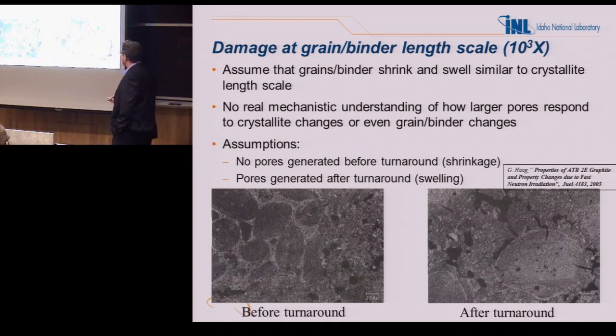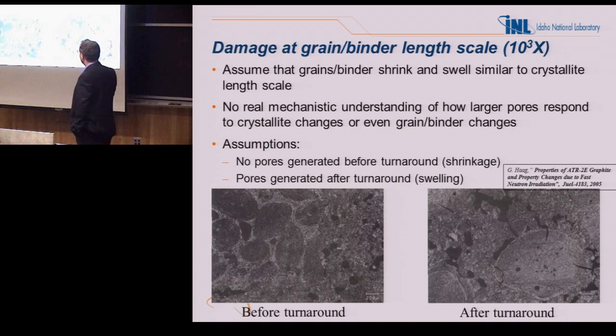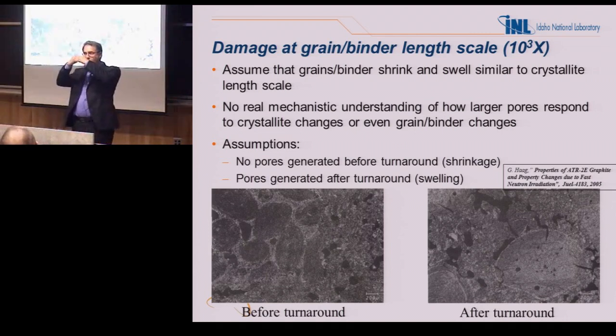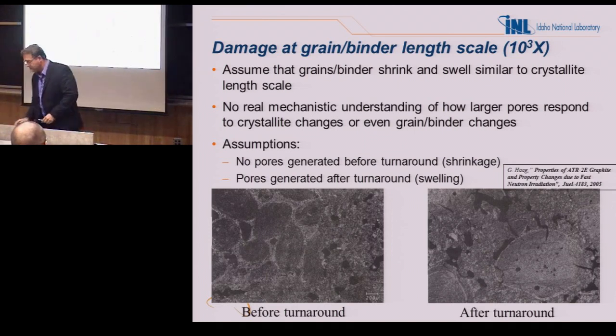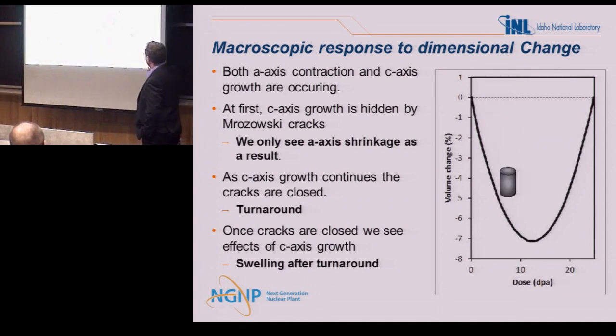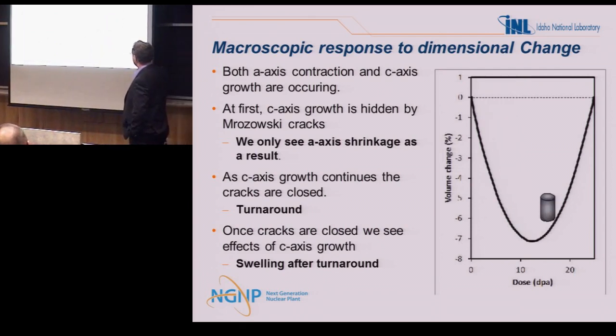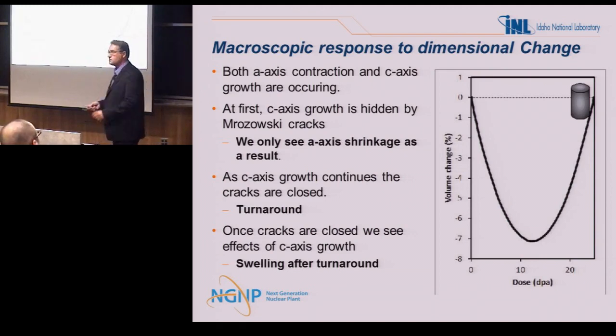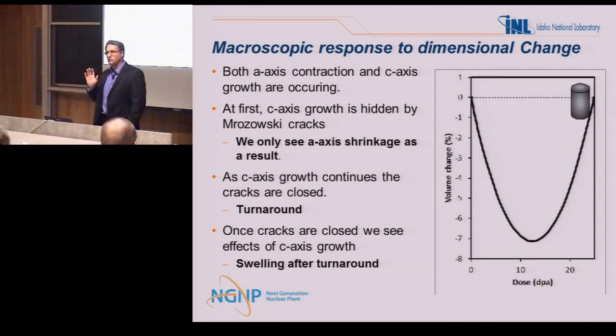So we assume that no pores are generated before turnaround, during shrinkage, but pores are generated after turnaround as these crystallites and grains start bumping into each other, and then they start forming cracks and voids in between the crystallites and the grains. As a consequence, you get only A-axis shrinkage right here because it's filling up those Mrozowski cracks. The turnaround is when the cracks fill up, and this is when you see the C expansion going on. Clear as mud?